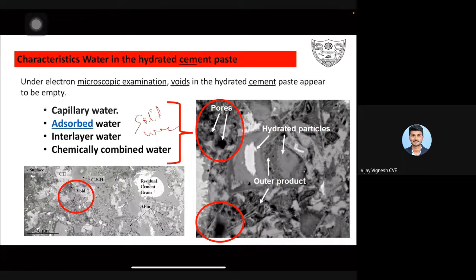Now I can take the SEM images of CSH, calcium silicate hydrate. It looks like a cauliflower, irregular in surface morphology. That CSH itself has some pores inside. Those pores have some water. That water also creates a lot of problems inside the concrete. So we have capillary water, adsorbed water, interlayer water, chemically bonded water, and so on.